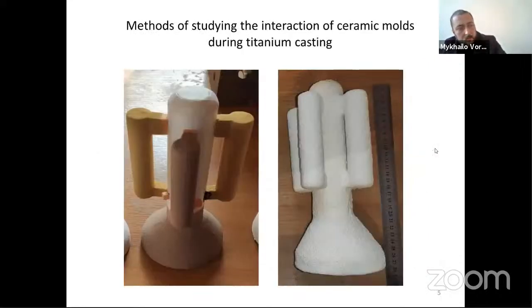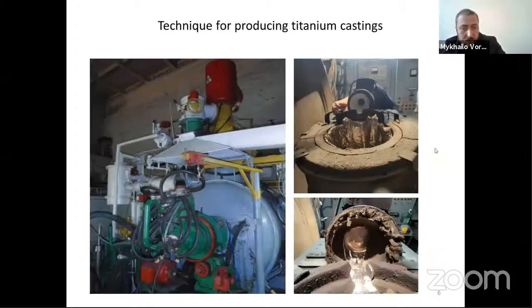Different contact shells were produced to investigate the features of ceramic-melt interaction. Inner layers were made of the chosen 3 types of ceramic, and the outer layer was made of large-fraction aluminum oxide. This is an example of our first training molds for pouring titanium and obtaining some pieces of metal to investigate mechanical properties and structure. This is our installation, and here we can see the furnace and 2 stages of experiments, before and after.